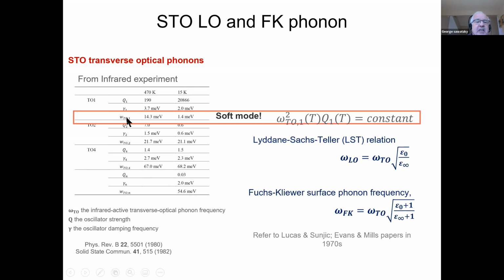And I'm going to talk specifically about this one. Here is the phonon frequency at 470 Kelvin. It's very highly dependent on temperature. This is a transverse optical phonon at 14 milli-electron volts, and it has quite a large width, and it has a huge Q. The Q basically is the static dielectric constant. Okay, that is the oscillator strength, the amplitude of the oscillation. If you go down to 15 Kelvin, that energy goes down to 1.4, it's overdamped, and the Q goes up to 20,000.